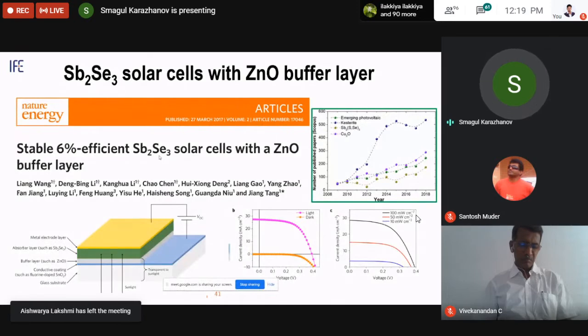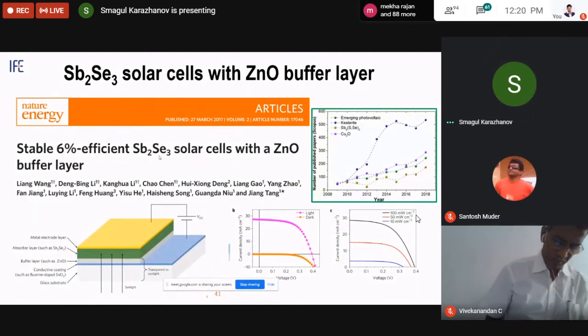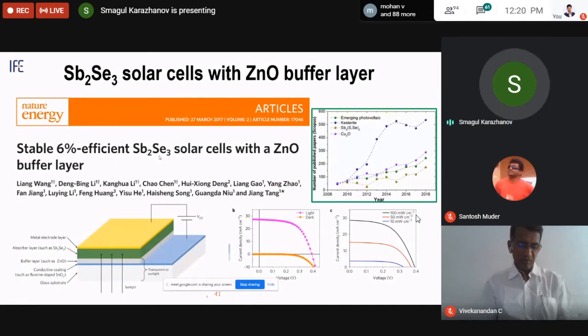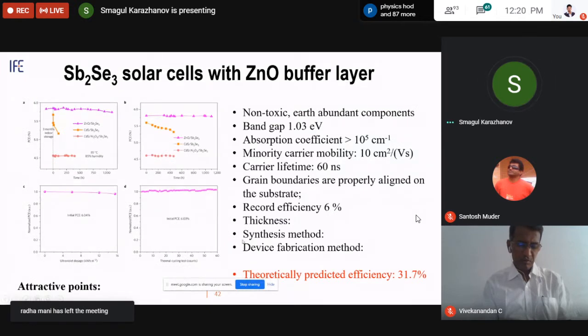However, in those materials, the cation possesses a 2+ valence state, whereas antimony here possesses a 3+ valence state. Then how to do it? One should play around here. Only according to some theoretical predictions, chlorine substituting an anion and a cation vacancy, this type of complex might provide p-type electrical conductivity, but this is under debate at present. But this is a promising type of solar cell.